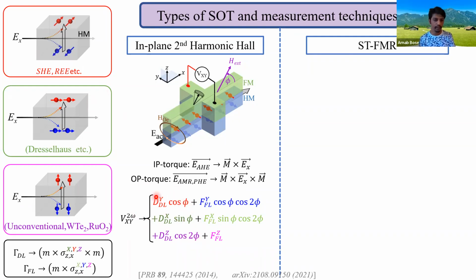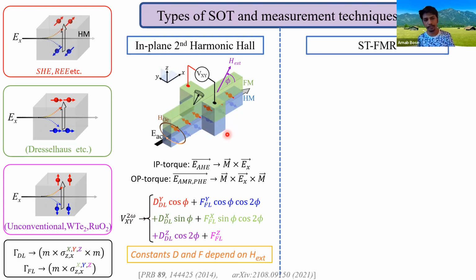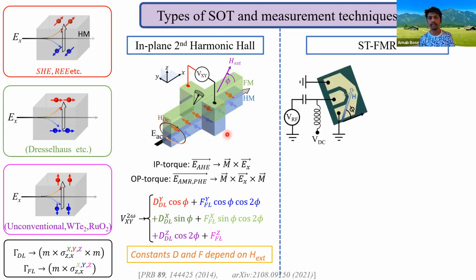Here, one important thing to note is that these coefficients also depend on the magnitude of the applied field. And typically it goes down when you apply a large magnitude of external field. This is how we can separate out the second harmonic Hall voltage that originates from the spin orbit torques from the thermal artifacts. Now, let me explain how STFMR works.